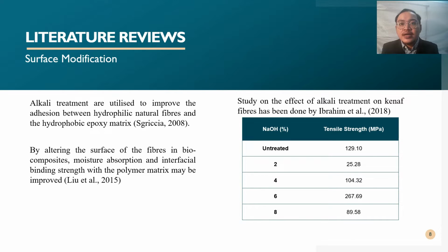A study has been done by Ibrahim et al. in 2018 on the effect of alkali treatment on the kenaf fiber. The result from the study showed that kenaf fiber treated with 6% of sodium hydroxide has the highest tensile strength.